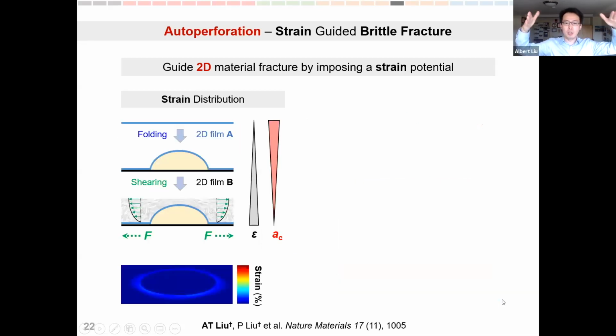If you imagine now what is happening within the given set of 2D material that is folding over into this array of polymeric pillars that we have printed, if we zoom into one of these particles, you see that as the 2D material folds over the circularly shaped pattern, very analogous to the process in which you fold a tablecloth over a circularly shaped table, right? Naturally, you will gain higher strain on the edge of this table, and translating to our molecular picture here, we're getting more and more strain around the polymeric pillar.